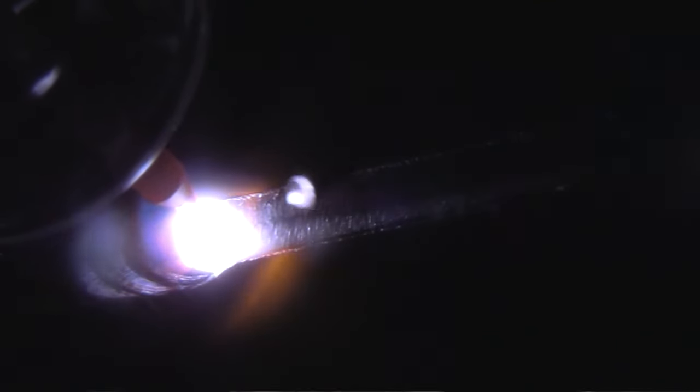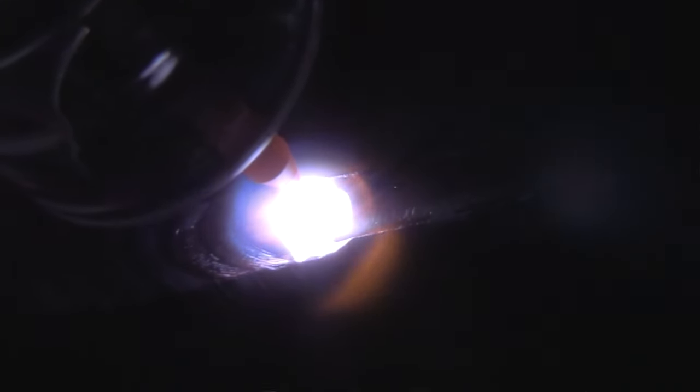Once you're too tight, you'll wind up sputtering and having to clean electrodes a lot. Here I am using a 3/32 electrode, so I'm 3/32 or less with my arc length, probably more like about a 16th.